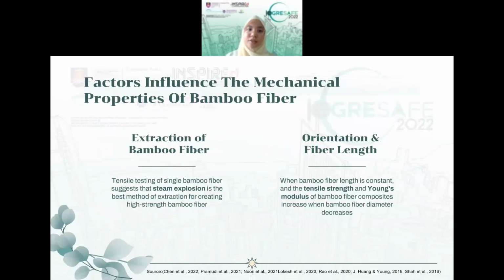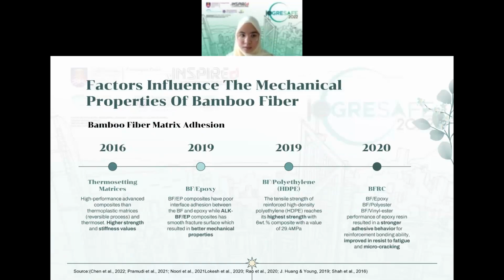So for the extraction of bamboo fiber, it is proven that steam explosion is the best method of extraction for creating high strength bamboo fiber. While for the orientation and fiber length, when the bamboo fiber length is constant, the tensile strength and Young's modulus of bamboo fiber composite will increase when the bamboo diameter decreases. So these are for the bamboo fiber matrix adhesion.